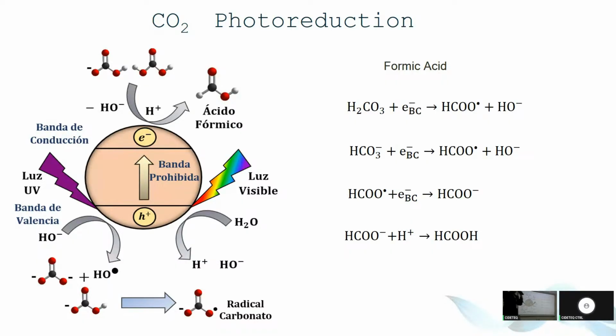Where the carbonate is formed, and then the carbonic acid. And then this carbonic acid becomes the main species that we are actually reducing by combining with the electrons in the conduction band. That also produces the formate radical, and then by proton transfers, we can obtain the formic acid. So at the end, the formic acid production will depend on all the pool of chemical species that we are producing, either by UV light or by visible light.